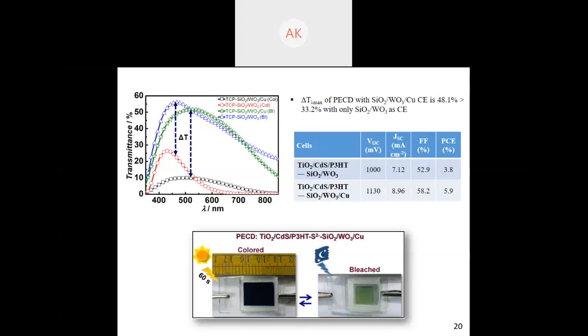Now, you see the lab scale image, what we have got when we have exposed it for 60 seconds under sunlight. We see the dark blue color. The same film, when we have kept it in dark for a couple of minutes, we see the bleaching occurring.